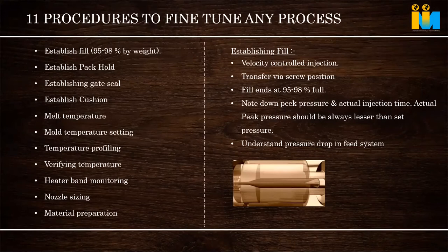Whenever we are injecting raw material into a mold, there are two stages. One is the injection phase. Next is the holding phase. In the injection phase, the requirement is to push the material at a higher speed and higher pressure into the cavity to fill the part. In the holding phase, after filling, the material slowly starts cooling down and shrinking.